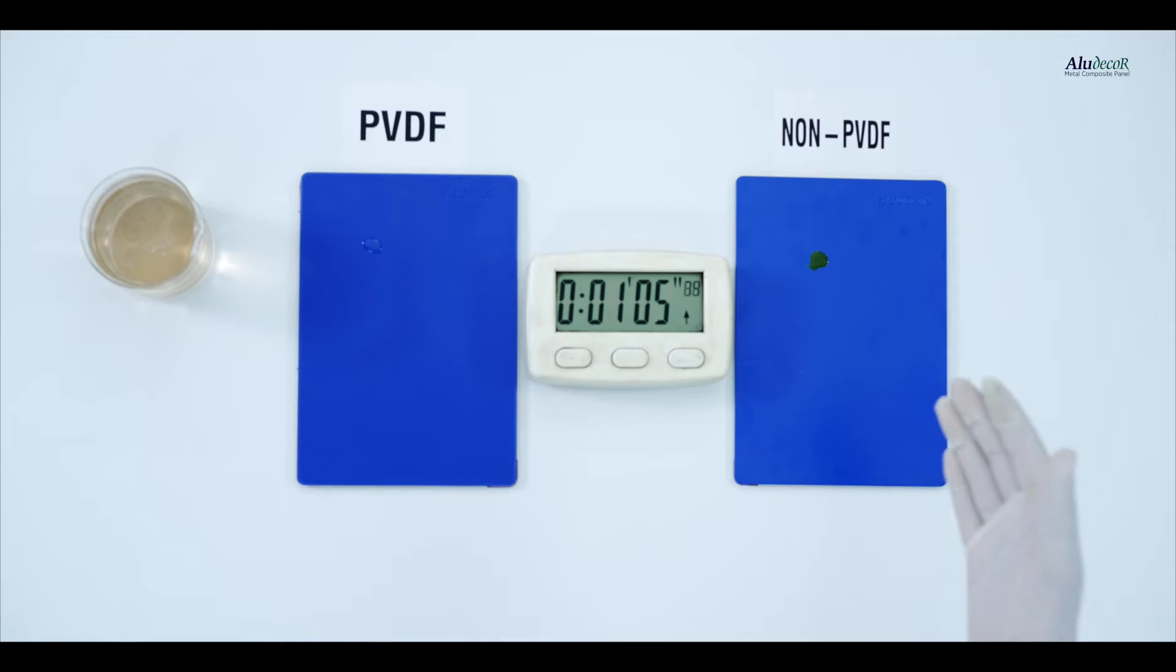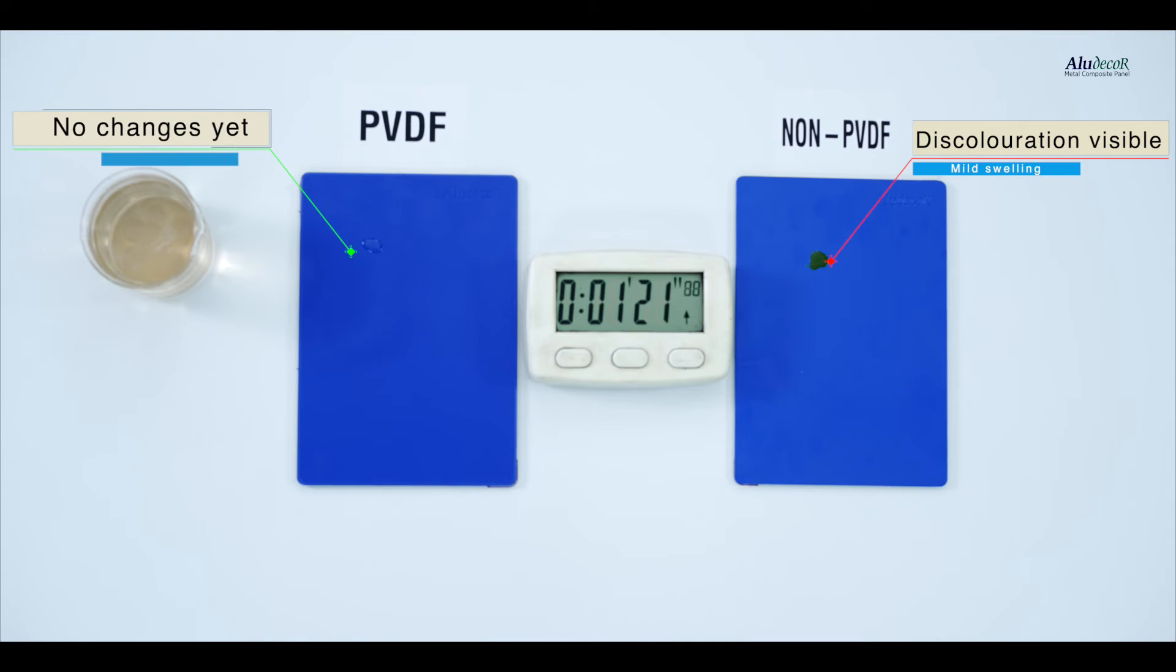We are almost close to 70 seconds and you can already see the non-PVDF samples have started discoloration and mild swelling. Now let's check PVDF. Here we do not see such change till now.